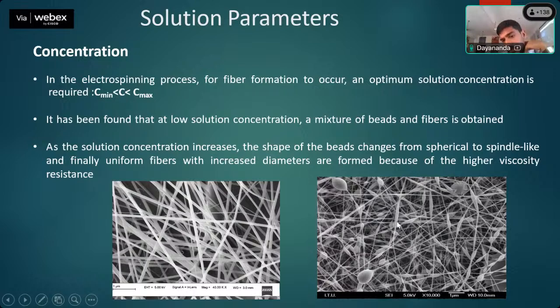On the other side, we have this beaded-like structure. This happened mainly because the concentration was not proper. It has been found that at low solution concentration, a mixture of beads and fiber is obtained. If the concentration is too low, to get the proper structural morphology, you need the optimum concentration.